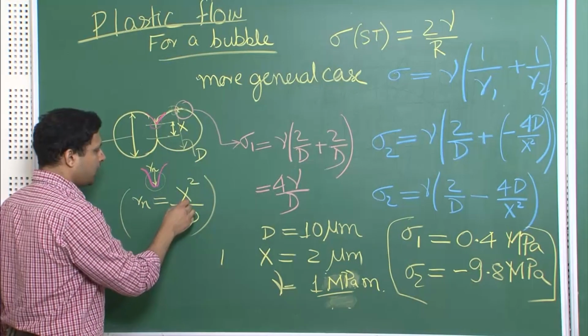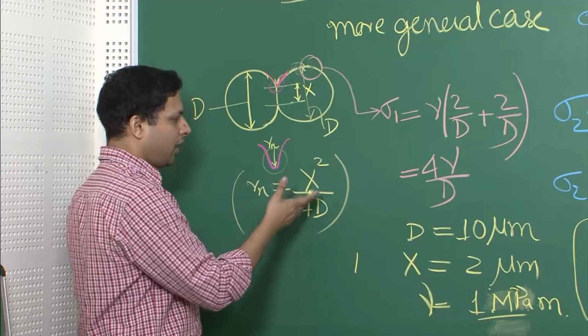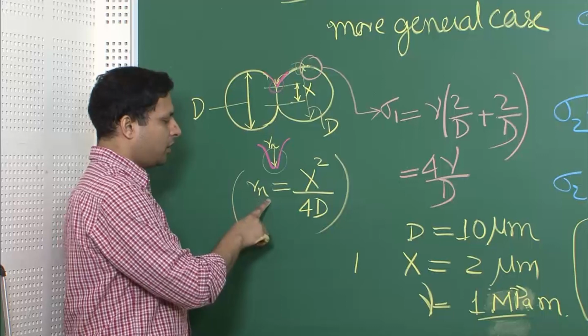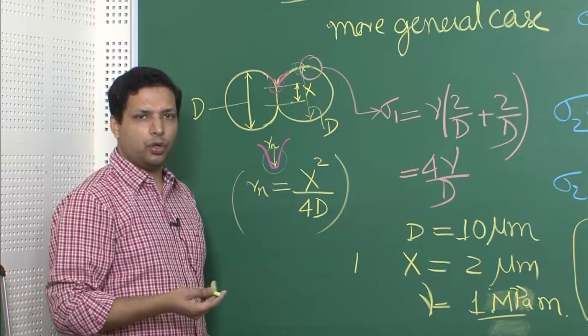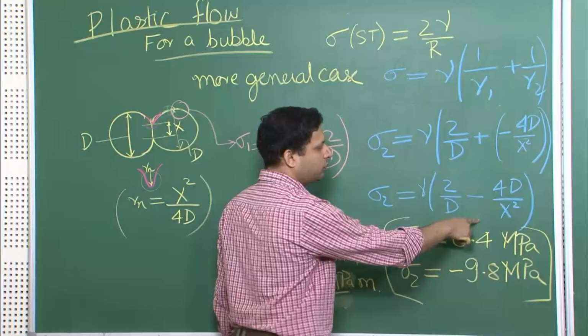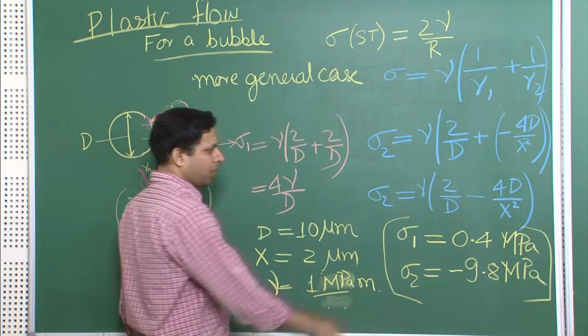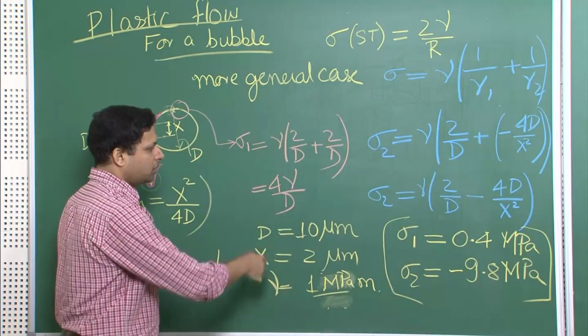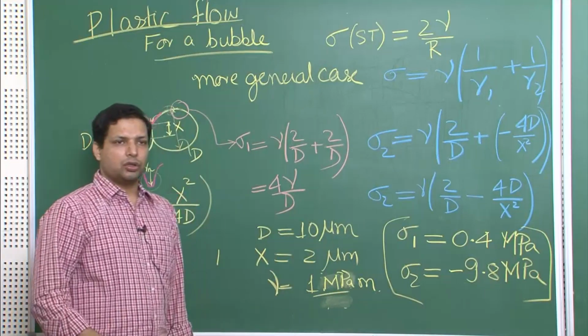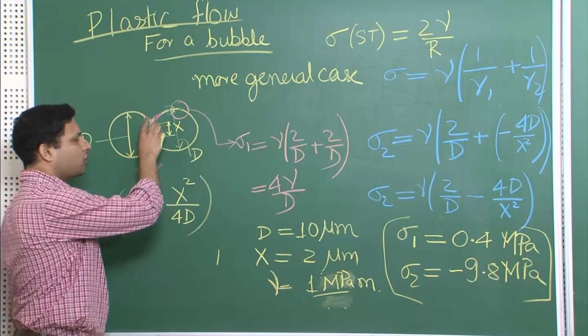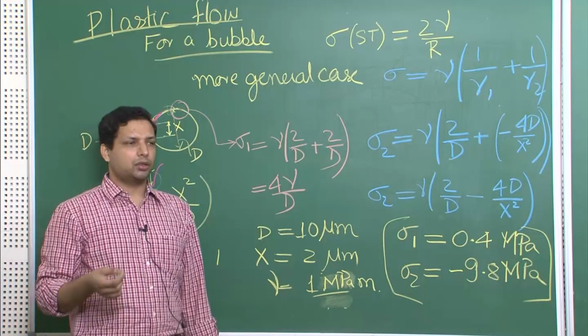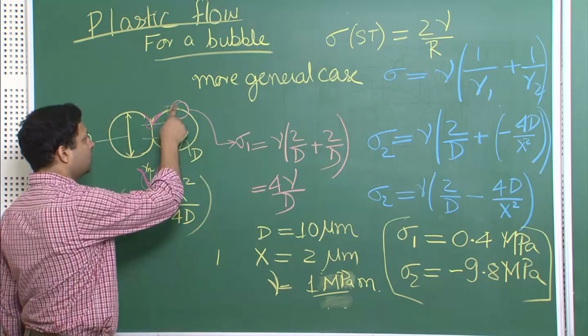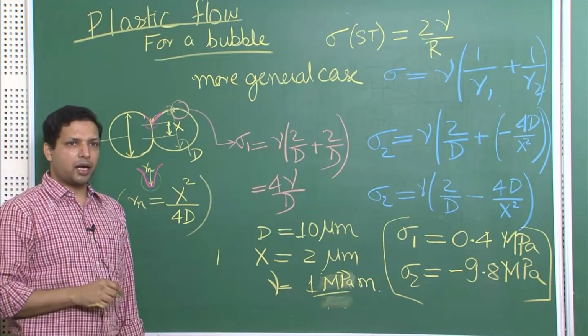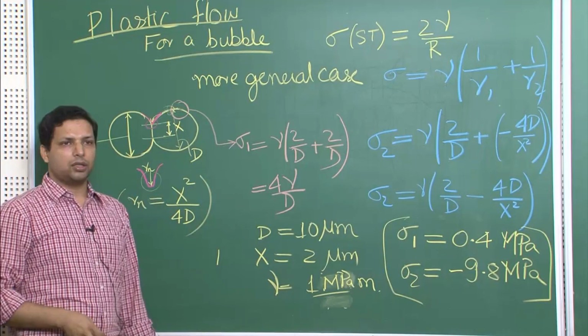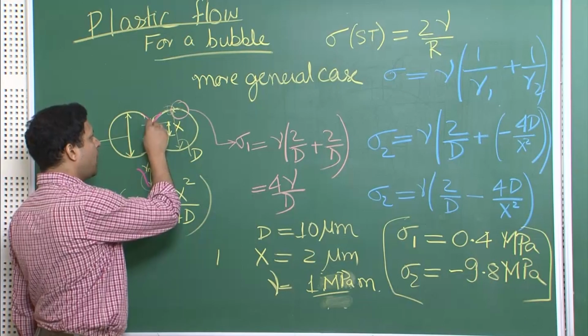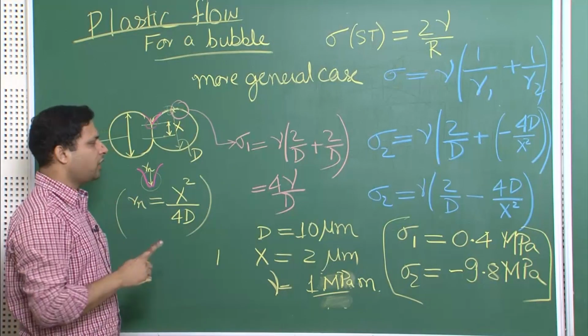Now, if you had x much larger, let us say if you increase x 2 times, then the radius of curvature of the neck would increase 4 times, which would mean that this value would become much smaller. If this becomes much smaller, that would mean that you will have less compressive stresses. So, again what it is saying, that as your neck grows, the driving force decreases, the total amount of compressive stress that is acting, or the stress gradient that exists over here will reduce as the neck grows. So, that is one thing that we understand from this.